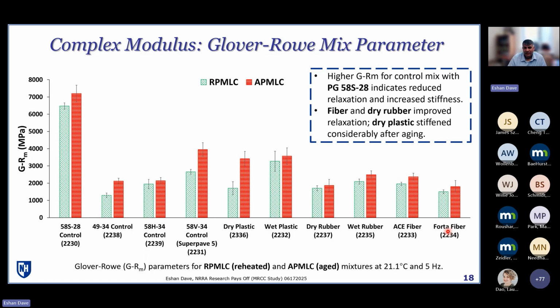So what we are seeing is that the control mixture, 58S minus 28, has a quite high Glover-Rowe parameter, which means it has reduced relaxation and increased stiffness. The fibers and the dry rubbers really showed good relaxation. They had a high phase angle.